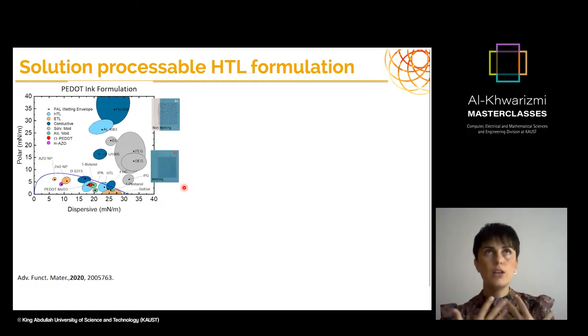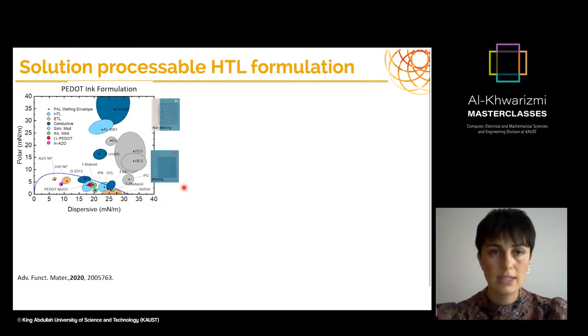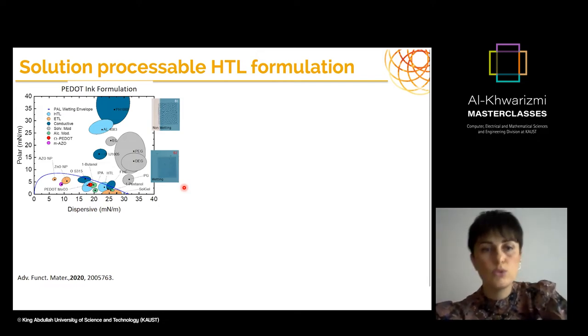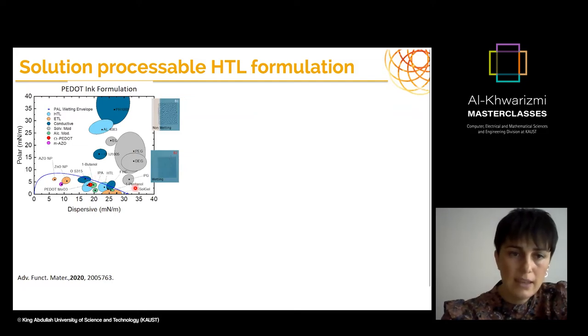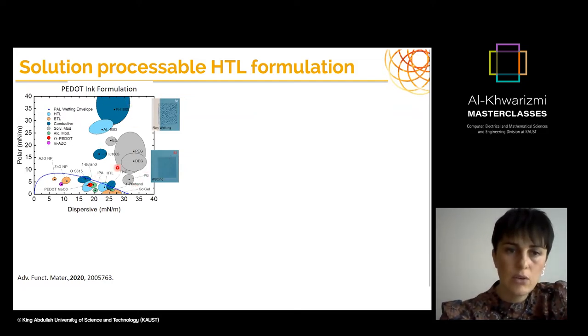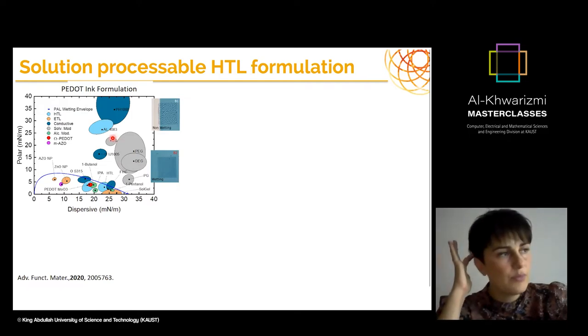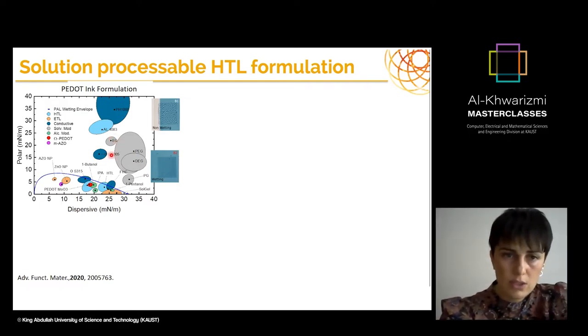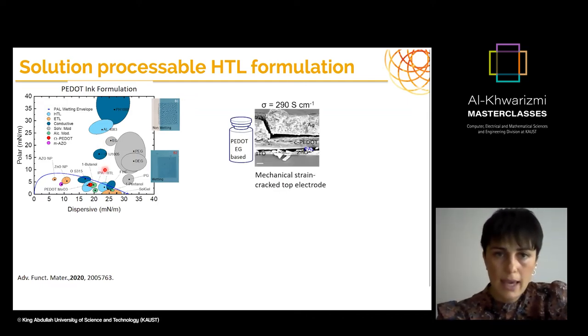So then we were like, okay, now we know the wetting behavior. Let's see what kind of hole transport layers are out there and if we will be able to fit onto our photoactive layer. So here, as you see, a lot of HTLs are staying outside of our wetting envelope. And most of the gray ones, which are used with surfactants in order to make them wettable, are also not really suitable in this case. Then the other ones, as you see, PH1000 or AI4083, or the combination with PEDOT, are also not very suitable. So if you try to make a layer on top of this with materials outside of your wetting envelope, we have observed mechanical strains, and then the electrodes cracked up.